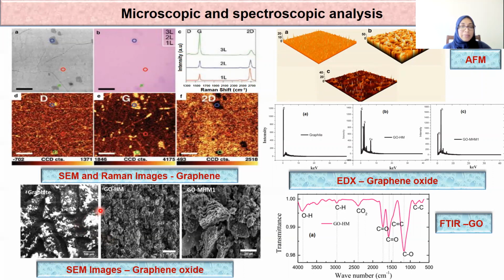And here, these are the SEM images of the graphene oxide. This is the SEM image of the graphene, and this is of the graphene oxide. And these are the EDS patterns. Here, this is of the graphite, and here there is no presence of oxygen, but here you can see the presence of oxygen, which shows that the graphene oxide has been fabricated.